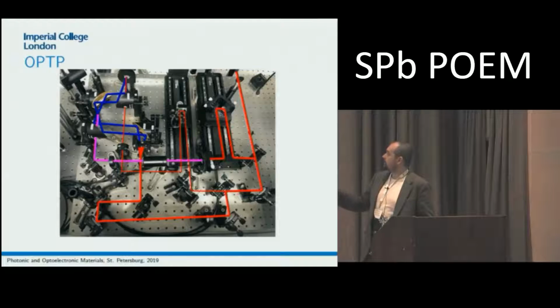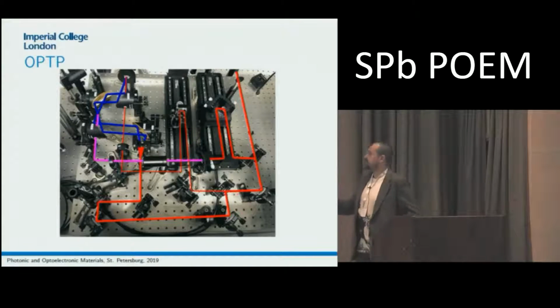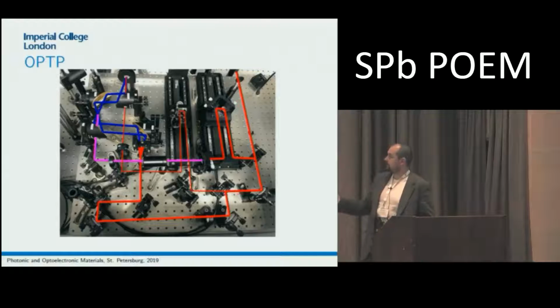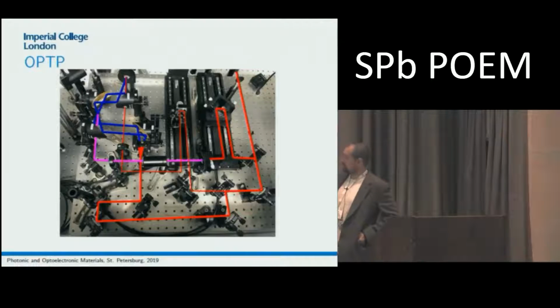So the incoming pump beam is converted with BBO and pumps the sample, which is situated in the focal spot of the parabolics. Then the beam that's pumping the emitter goes through some extra delay for beam path matching, and pumps the photoconductive emitter. Then terahertz is collected by parabolics, focused down with parabolics with shorter focal distance, and coupled into zinc telluride for detection. And the probe beam is independently delayed, and electro-optic detection is used to detect